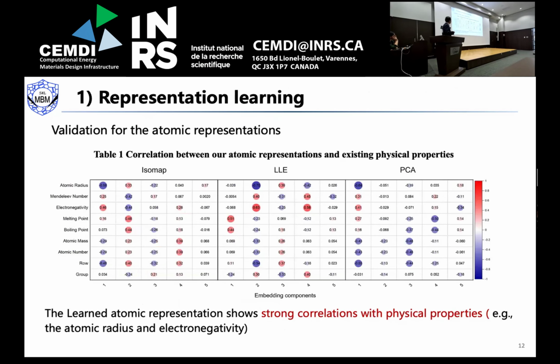And we also make some comparisons to make sure our atomic representation is okay. So we calculate the Spearman correlation between our method and the existing physical properties. We found that our method shows strong correlation with the atomic radius, the atomic number, and also the electronegativity and similar properties. That means our method shows a strong relationship with the physical properties.